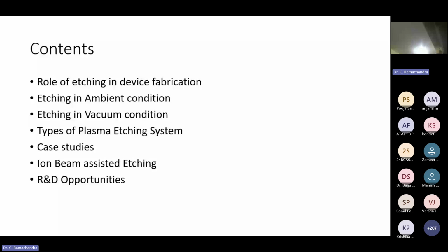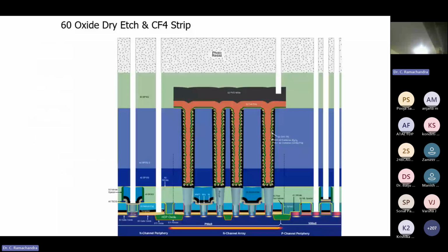So as I said, now you can see these are all the structures. I need to make these kinds of vertical etches. The diameter or size of these vias is typically 0.2 micron, 0.3 micron, and the depth is a few microns. How do I etch this kind of vertical hole without disturbing the adjacent structure? It looks simple. But because I am using plasma, plasma means ions. Where I am injecting the gases, the plasma is created at the surface, and because of ionization or a field, they get ionized. But what is the probability that these ions go inside? Because if they do not go inside, they cannot etch. So what is the probability these ions move to the inside? That is one of the biggest challenges.